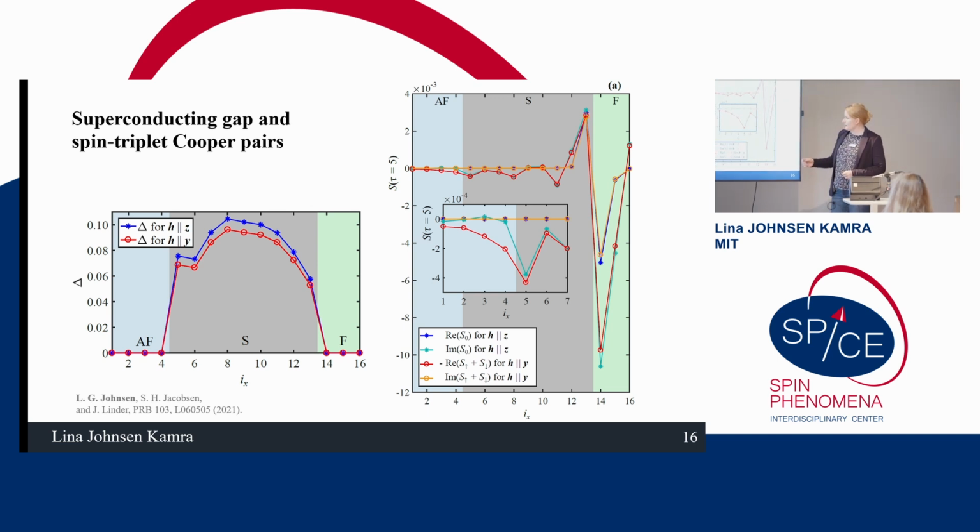If we now look at the odd frequency spin triplets, here particularly in the inset close to the antiferromagnetic interface, we see that the triplets generated here at the ferromagnet have different behavior when you have a perpendicular and a parallel alignment. When it's parallel, it dies out rather quickly, while here in the red curve, where it's perpendicular, it can leak far inside the antiferromagnet due to these triplets being equal spin compared to the antiferromagnet.